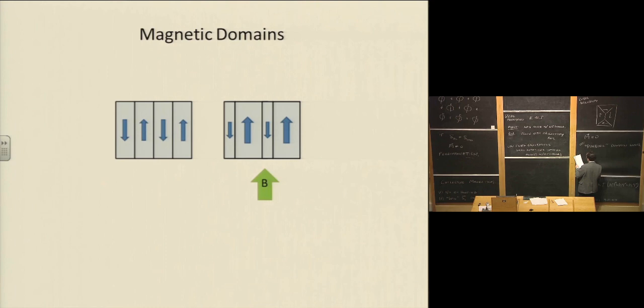And the way you typically pin a domain wall is with disorder. Whether one is trying to design a magnet for use in electrical motors, a magnet that will stick to your refrigerator, or a magnet for a magnetic disk drive, the whole art to making good magnets is to figure out how to make the disorder prevent the magnetic domains from moving back to their original configuration where the magnetization goes back to 0. Okay, so why is it that disorder is going to help you?